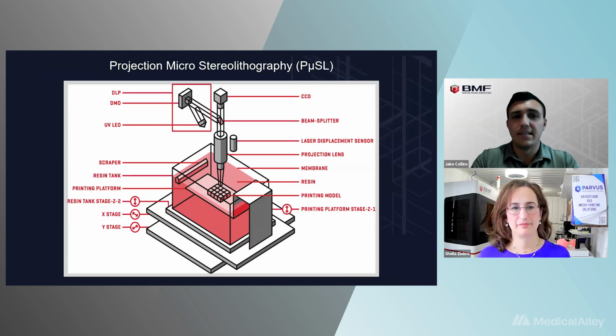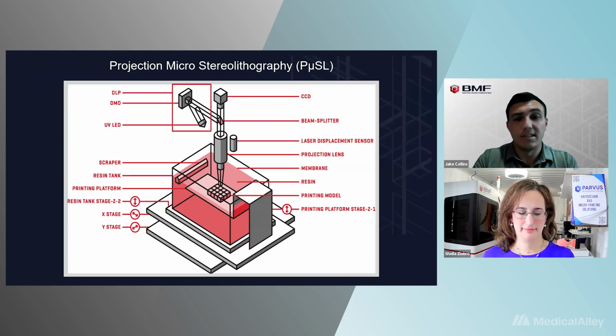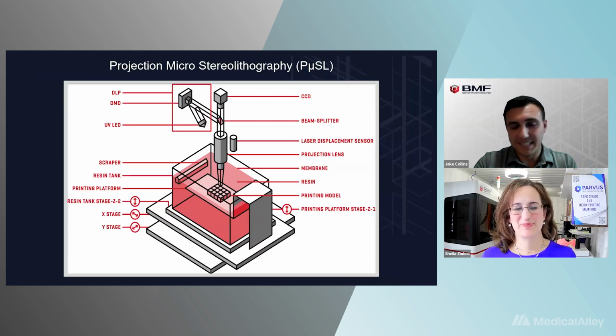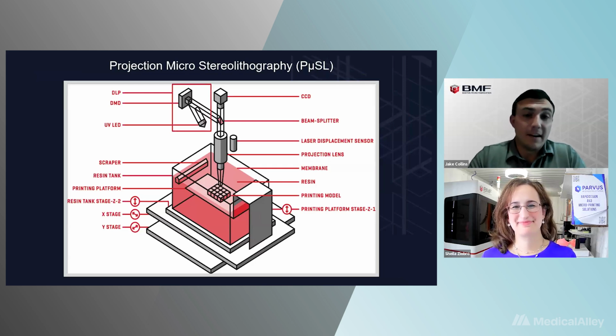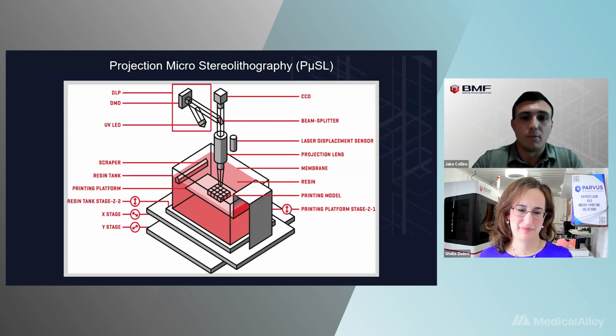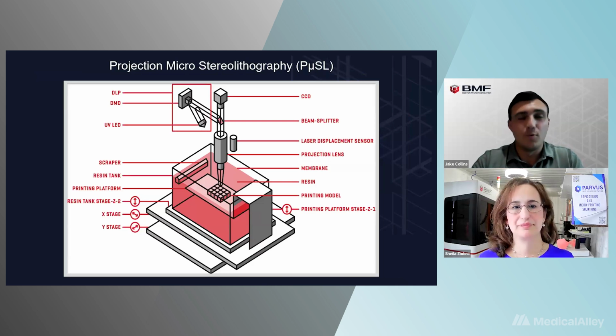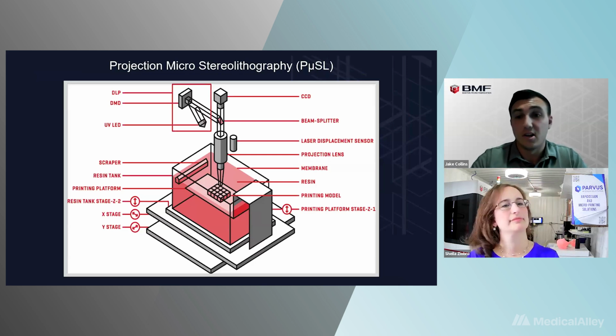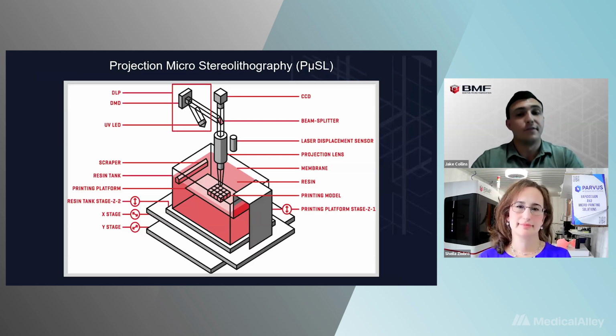And another thing to hit on here is another reason why we're able to achieve this high resolution is that we are an open platform system and have customizable parameters. So it allows you to get extremely detailed on energy dosage going into the builds layer by layer to achieve that higher resolution and feature accuracy. Typically on most other systems, you're using general settings, or there are material specific settings that will get you good parts. But when you're talking about, like Sheila's saying, plus or minus 25 microns, we're talking about one white blood cell here. You want to make sure you have full control over all of those things. So our open platform system allows you to do that. And with that open platform system, it gives you the ability to use a wide range of materials, both BMF specific materials, as well as custom or third-party materials. And we can actually talk about a few of those on the next slide here.